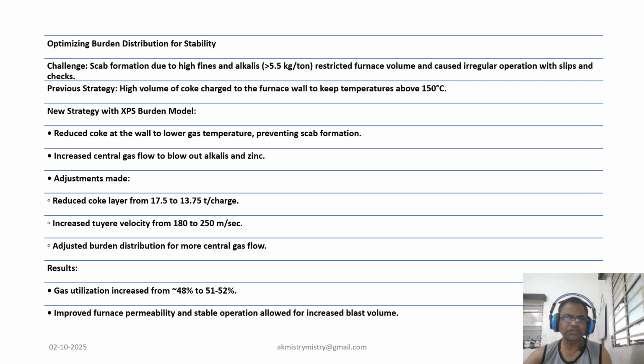And this gave a result. Gas utilization increased significantly from around 48 to over 51%, leading to better permeability and allowing for higher blast volume, which in turn boosts production.